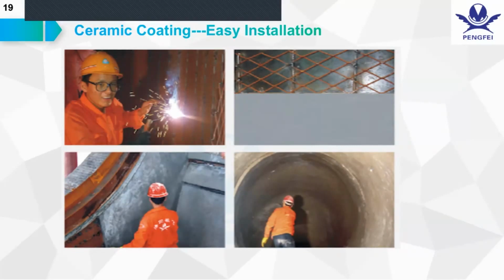Ceramic coating actually is a very easy installation way, like castable. They just have the metal mesh and fibers, then match with water and apply in the pipe. So as we said, what's the difference between the ceramic coating and the castables? Because they both are wear-resistant materials. You can see the big pipe. With ceramic coating, we only need to apply 25 millimeter thickness. When we reach the same wear rate function, the castable usually has to apply about 100 millimeter. So the thickness is about 4 times more.